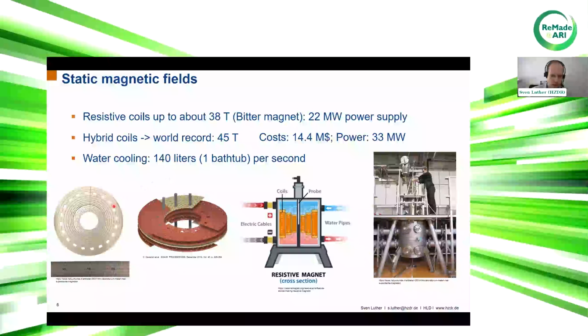So these bitter magnets consist of so-called bitter plates, which you can see here. This is just a copper plate, and it has a hole with a diameter of roughly 10 centimeters. And this is the bore of the magnet, in the range of, let's say, 5 centimeters, where our cryostat, our probe and our sample also have to fit inside. And as you can see here, this plate has lots of holes inside, because if you apply these high currents, they also heat up a lot. So you need water cooling for these plates. And here we have 140 liters of water, so let's say 1 bathtub per second running through these plates to cool them down.